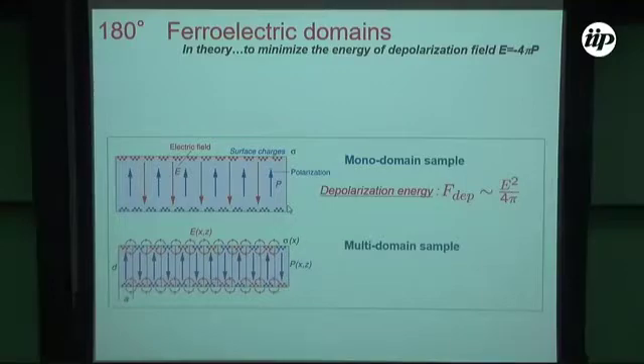To give you an idea about the effect, we can quite simply calculate the renormalization of the critical temperature, for instance for a ferroelectric with a transition temperature, let's say, of 300 Celsius or Kelvin, it's not important. We can calculate what will be the renormalization of TC when we take into account the depolarization field. And we obtain that the transition in the ferroelectric will occur at minus 10,000 Kelvin. So this is how huge this effect is. But again, in the macroscopic sample ferroelectricity exists because we have some external type of screening. And actually, when we remove all of the screening, according to Landau and Lifshitz, the system will split into domains.